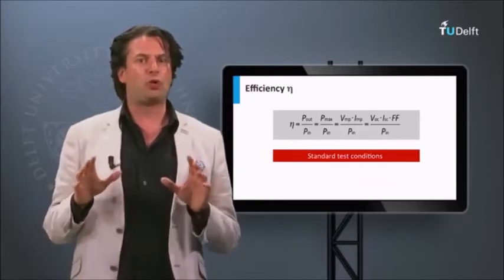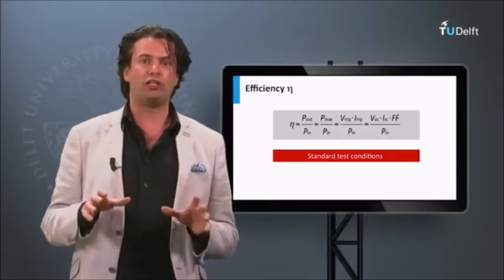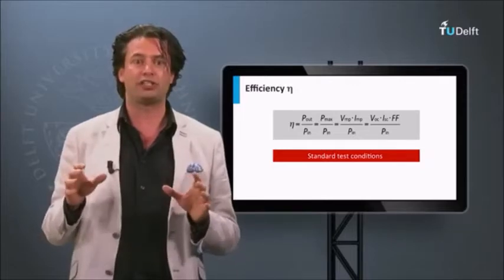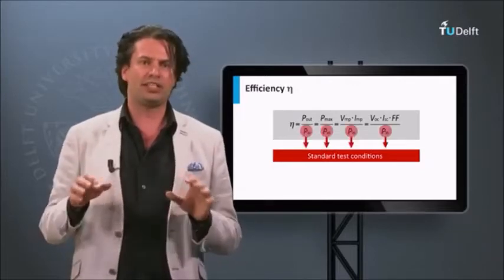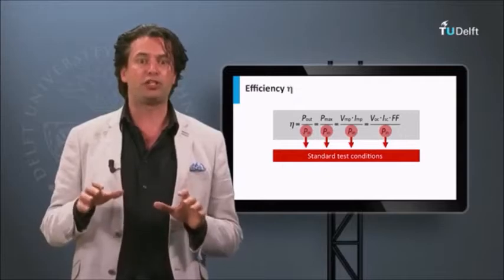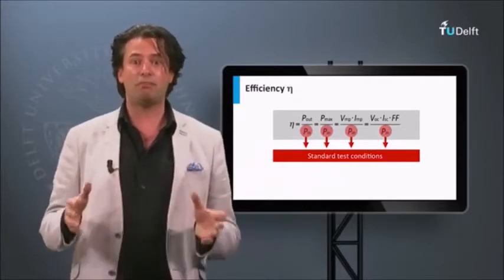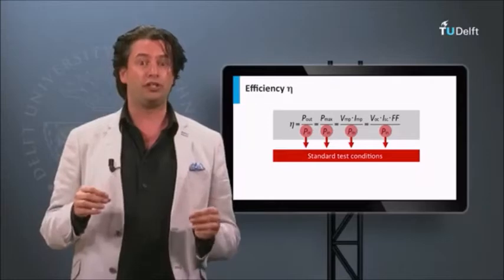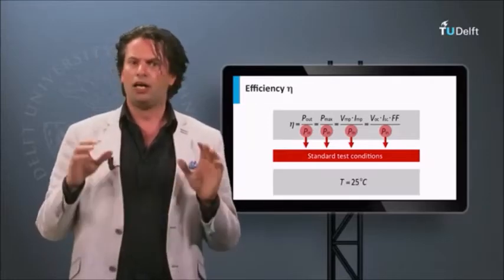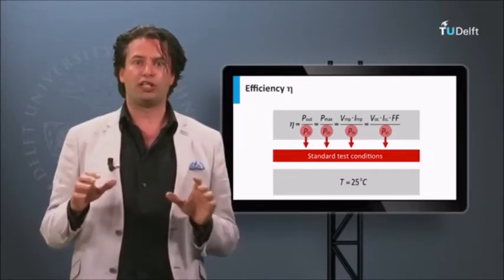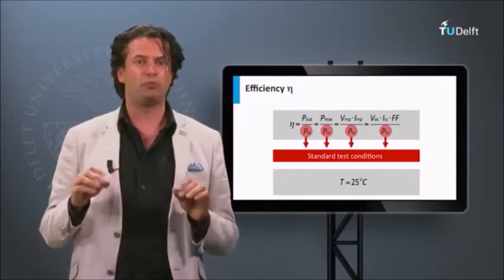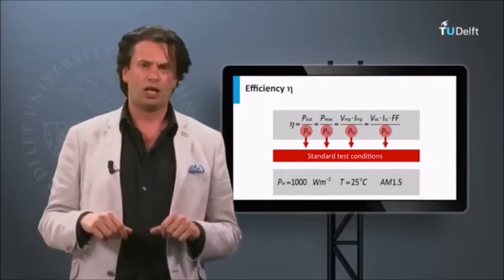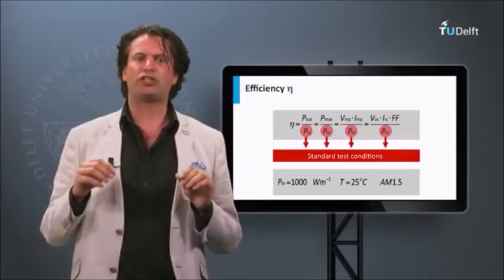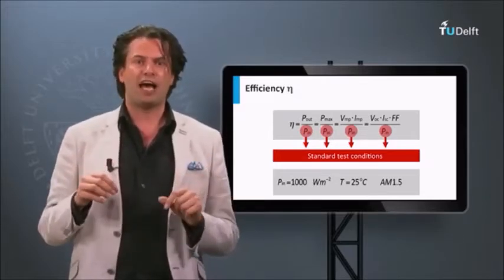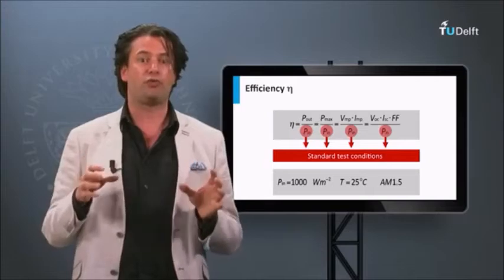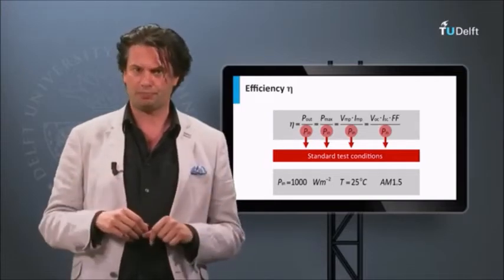To be able to compare the efficiencies of different solar cells, the so-called standard test conditions have been introduced. The standard test conditions describe the conditions for P in and the temperature of the solar cell during the JV measurement. The temperature of solar cells in the standard test conditions is determined to be 25 degrees Celsius. The solar spectrum has the spectral shape of AM 1.5 and a total irradiance of 1000 watts per square meter.